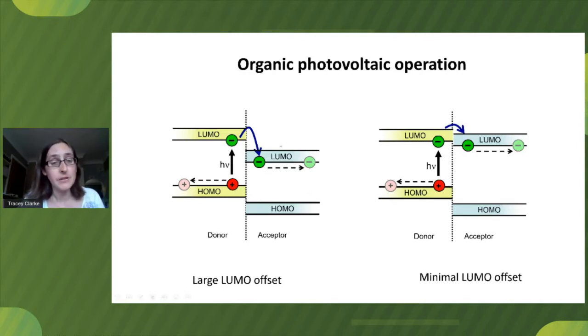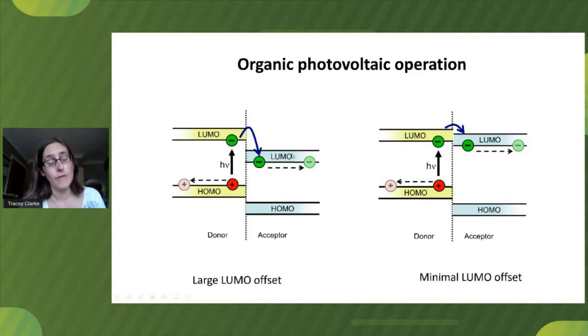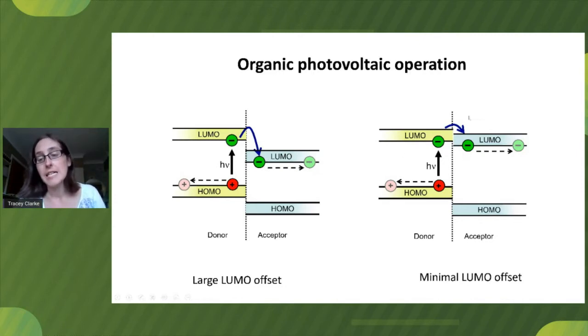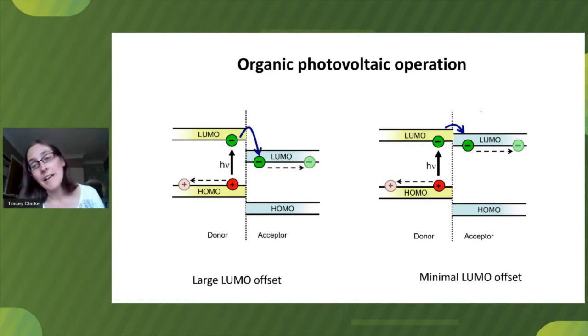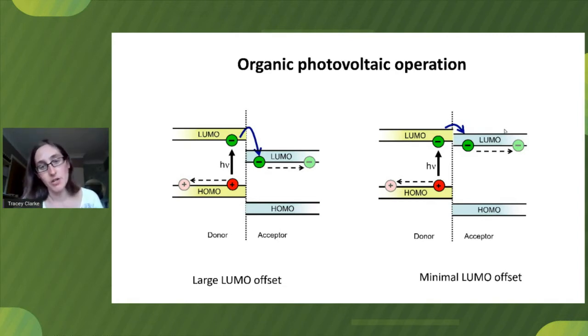However, this isn't an ideal situation because it typically leads to losses in voltage, since the voltage of an organic solar cell is related to the difference in the HOMO of our donor and the LUMO of our acceptor. So one of the things people have been looking at recently, particularly with regard to non-fullerene acceptors, is to minimise this LUMO offset. This then enhances the maximum voltage you can get — but does it minimise the charge photogeneration? Interestingly, it seems we're still able to get efficient charge generation.